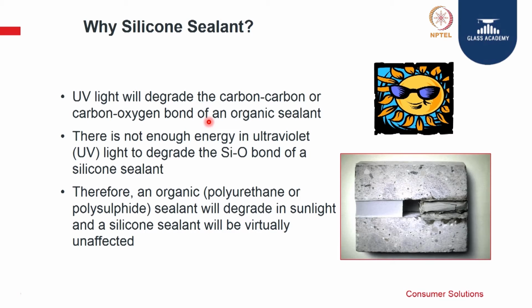I will tell you one simple example. In the automotive industry, people use polyurethane for bonding the windshield. But if you look at the windshield, it has a black ceramic paint around the perimeter to protect that sealant from being exposed to atmospheric conditions. The UV degrades the PU, so that is the reason they frit it.